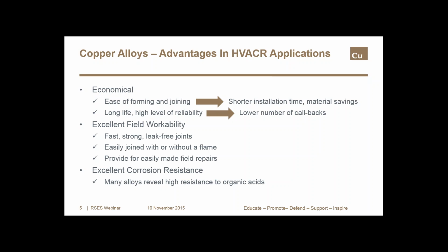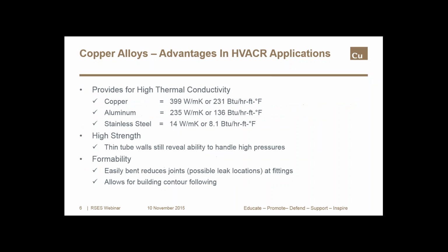Copper alloys are inherently resistant to corrosion. Certain alloys are resistant to the presence of organic acids, and copper tubes made from these alloys are specifically being marketed for air conditioning and refrigeration applications, such as evaporator coils. The thermal conductivity of copper is more than 60% higher than aluminum and about 30 times that of stainless steel.